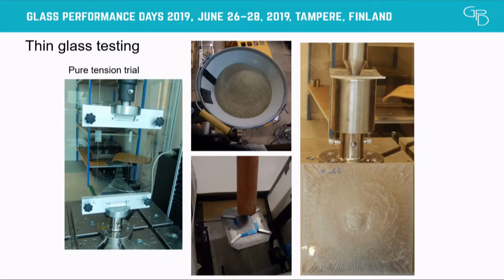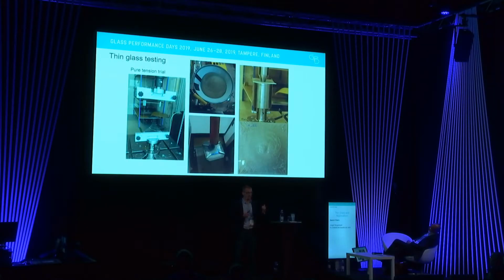Also, another important property that people always ask me about is the fragmentation properties. Because it's known that once you have very thin glass, the strain energy that the chemical tempering introduces in the glass can be such that it could trigger some degree of safe fragmentation. This picture shows you a panel after the test where you see a fairly coarse fragmentation, but I want to warn you, this coarse fragmentation is only there because of the test load that was introduced. Normally, if I was impacting this glass with a spring-loaded punch, it will break just like annealed glass or even less than that.